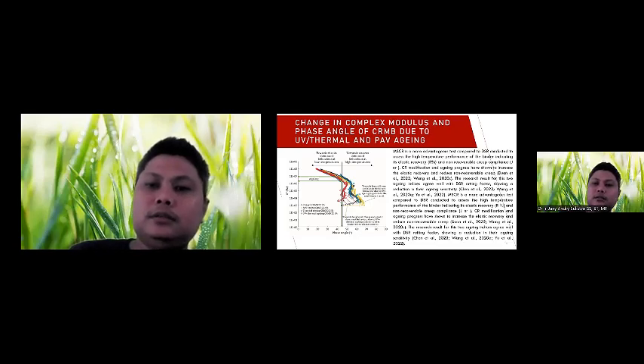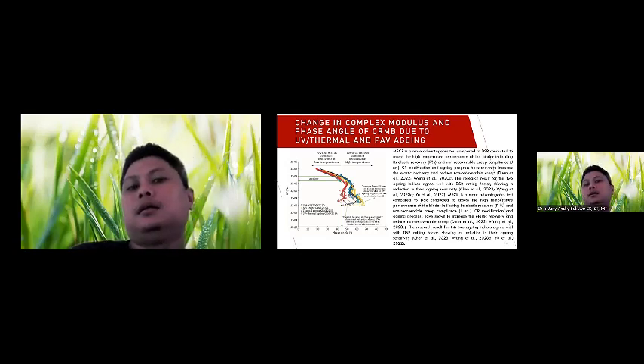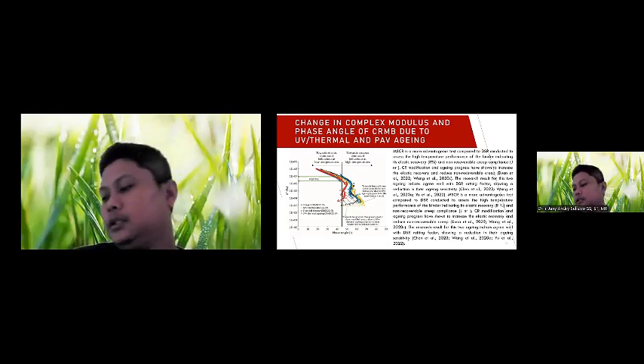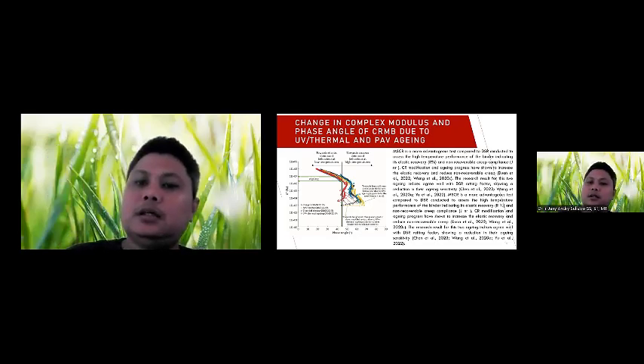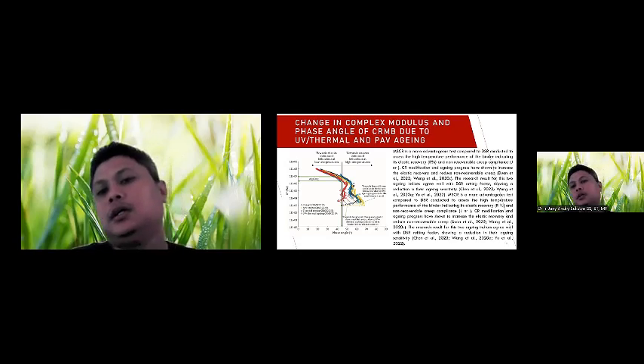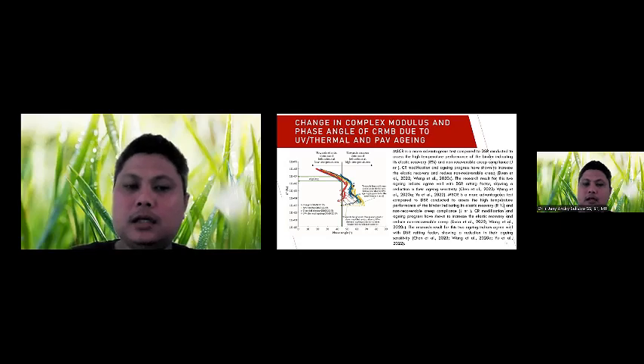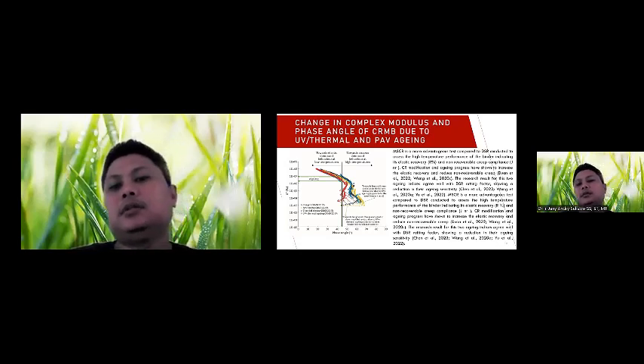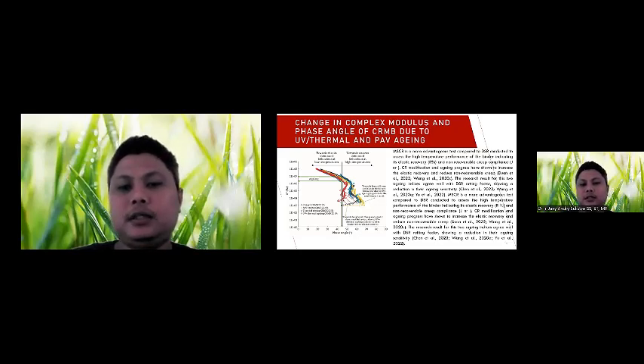For this article, we can have a conclusion about the advantages of using the DSR to evaluate high temperature performance. The binder's non-recoverable creep compliance has shown increased elastic recovery and reduced non-recoverable creep. The results for these two aging conditions agree well with the DSR rutting factor, showing a reduction in aging sensitivity.